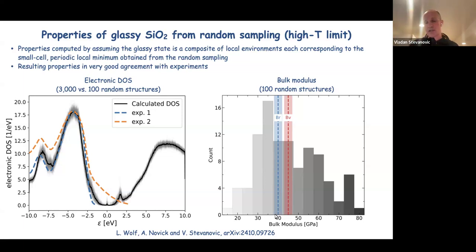They go somewhere between about 39, which is the lower value of this confidence interval, to about 46, which is the upper value here. The experimental results for SiO2 glass range between 36 and 39 gigapascals. So again, we are reproducing the bulk modulus of glassy SiO2 using this scheme within typical errors of about 10% that DFT methods usually make in bulk modulus.